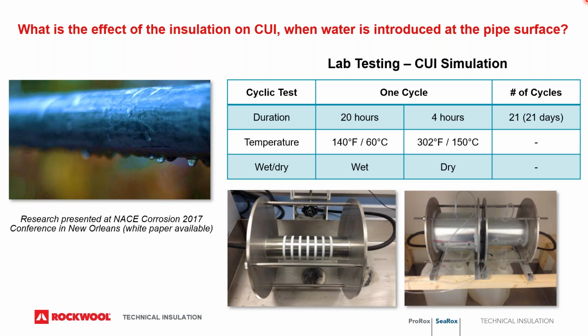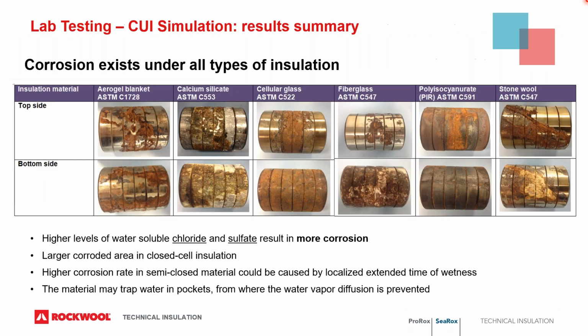The test rig is exposed to a wet and dry cycle. You get 20 hours of wet, and then we allow for a 4-hour dry. We did this for 21 days to find out what would happen. And so here are some of our key findings as we look at these images of corrosion on the top and bottom sides of the pipe.